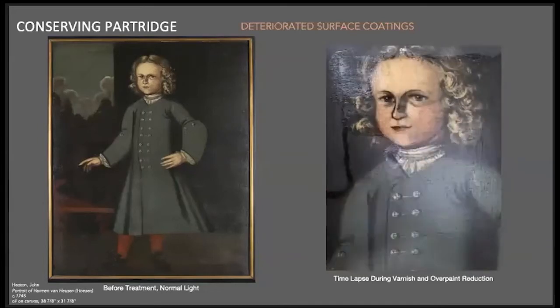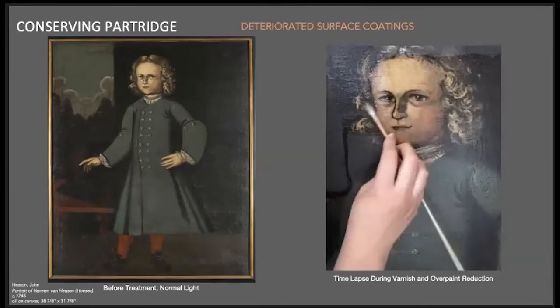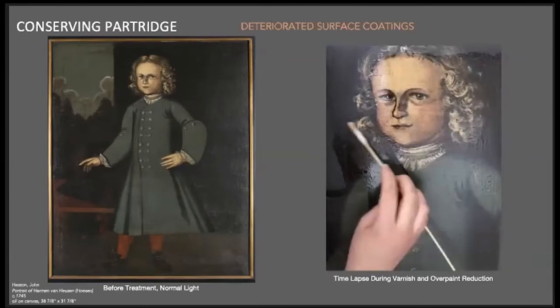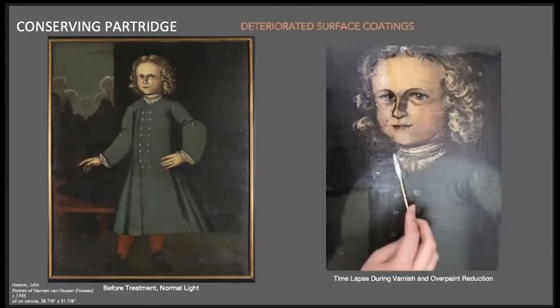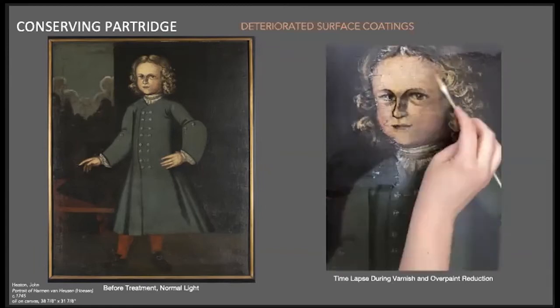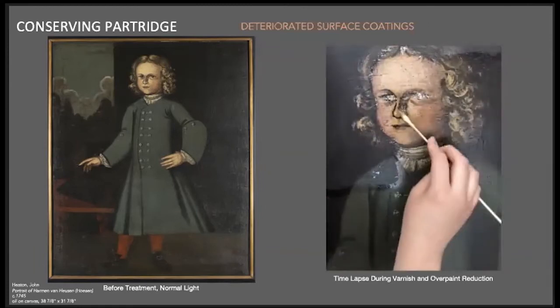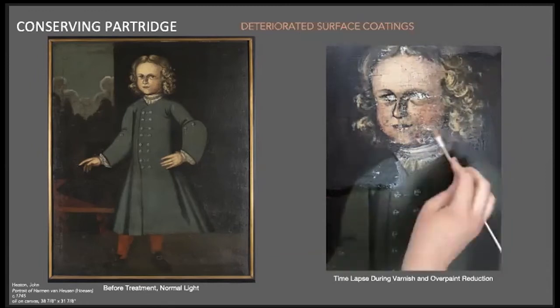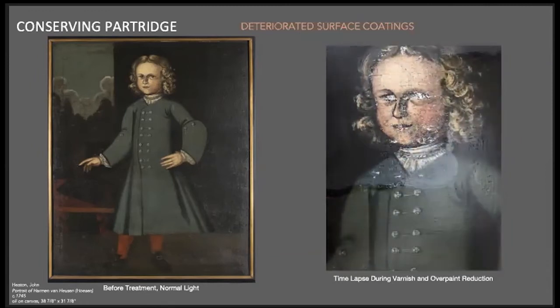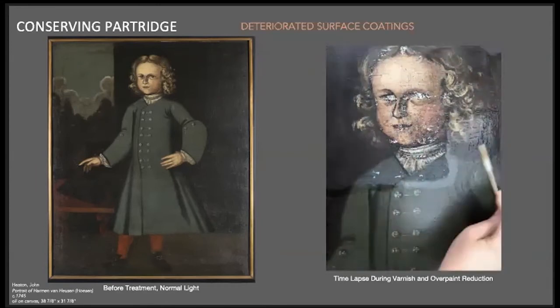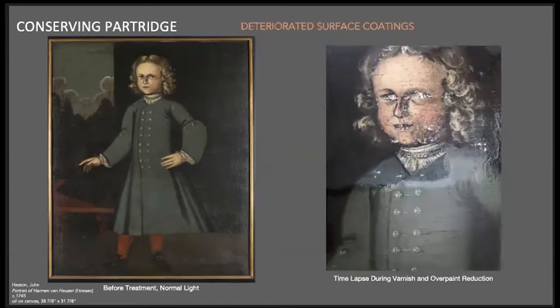As you can see in the time-lapse video on the right, taken during cleaning, this portrait attributed to John Heaton in the Albany collection had a significantly yellowed varnish. Reducing the yellowed varnish allows the true tones of the sitter's hair and complexion to return to life, but it also reveals the extensive loss in the face. At some point in the painting's life, the eyes were physically abraded away.